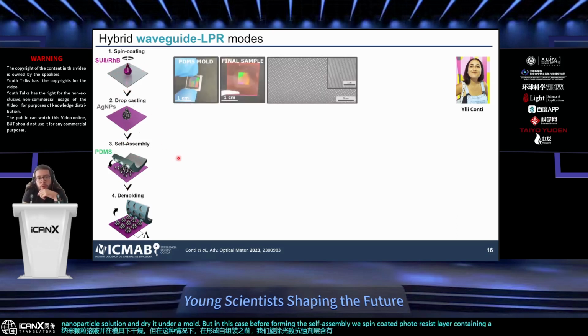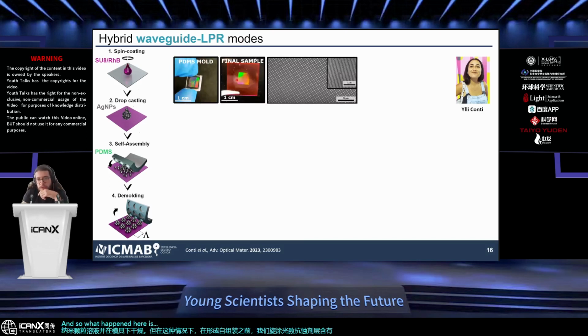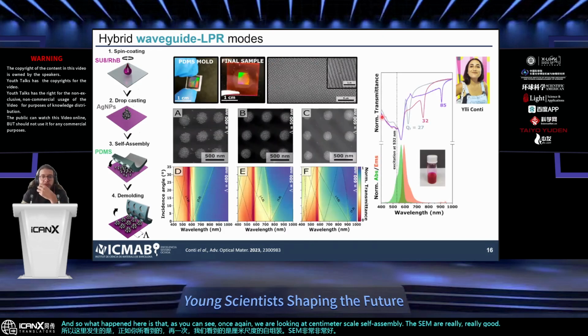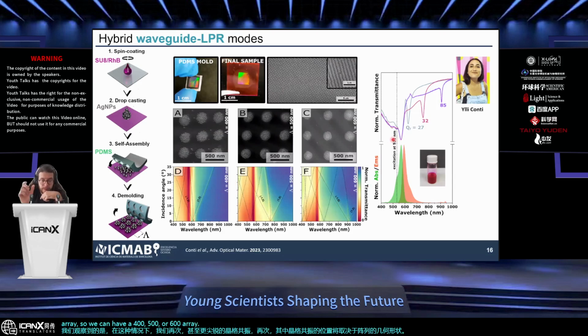And so what happened here is that, as you can see, once again, we are looking at centimeter scale self-assembly. The SEMs are really, really nice. And what we observe is that in this case, we have, again, even sharper lattice resonances, where the position of the lattice resonances depends on the geometry of the array. So we can have a 400, 500, or 600 nanometer array spacing between each cluster, and then we will observe the lattice resonance at around 630, 750, and 900 nanometers, more or less.